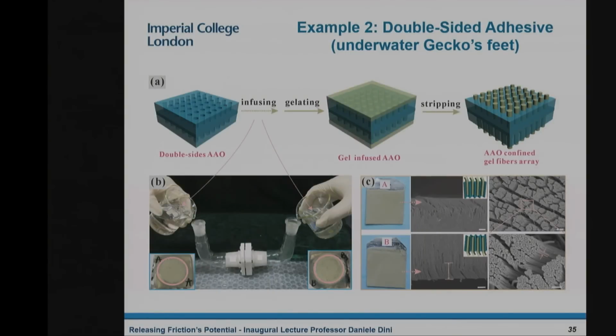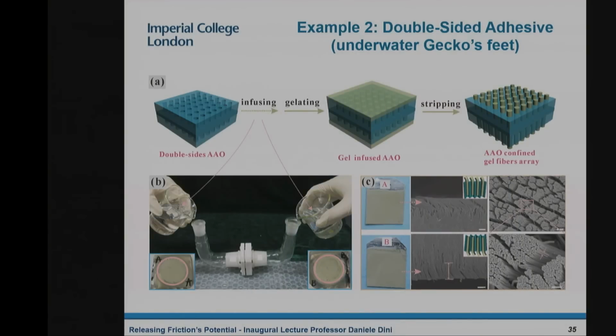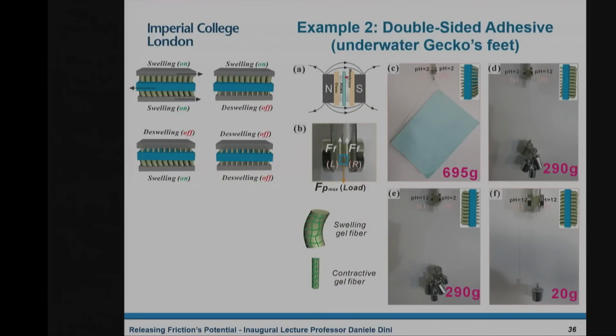But the good development of this comes from the fact that once you know that you can tune and switch your friction between surfaces, you can think of tons of things you're going to do with this. So one of the things they did, and we did the theoretical explanation for this, was to create, this time, a system with 2 of these surfaces on each side. And the idea was that thanks to these hydrogels, which are actually very fibrous, and having them on both sides, you can generate a structure like this, and you can think of putting it between 2 surfaces. So imagine you're now placing this system between 2 surfaces, and you're squashing the 2 surfaces with a certain load.